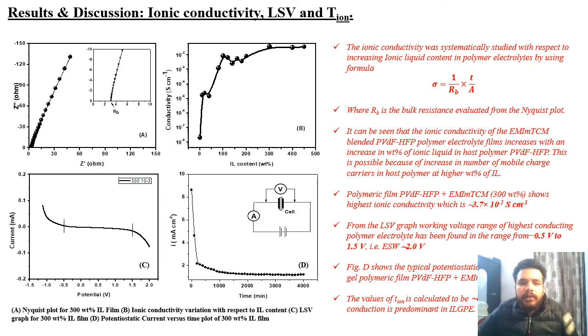First of all, we have taken impedance spectroscopy of all the films, and then we draw the Nyquist plot out of it, and then we calculate ionic conductivity from them by using the formula given here on the screen. After calculating it, we draw a graph between conductivity and ionic liquid content. Here you can see that the highest conductivity is shown by the 300 weight percent film, which is 3.7 into 10 power minus 2 Siemens centimeter inverse.